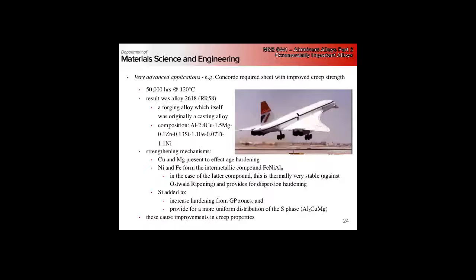So the basis for this alloy was actually a casting alloy, which was slightly modified. You can see we've got a soup here of all the usual players: aluminum, copper, magnesium, zinc, silicon, iron, and some nickel, some titanium. You could really take the titanium out and substitute zirconium in, and you'd have something very similar, both group four metals.